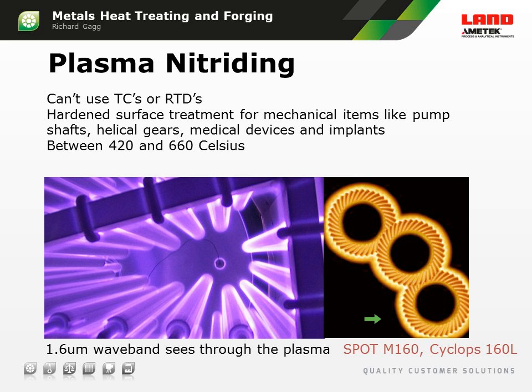And so it can be used for years and years and years and not crack, because it is slightly flexible, and only the areas which contact in the gears have this hard surface. Now, if you put a contact device into one of these plasma nitriding areas, the contact device will be contaminated by the plasma coating process. So again, the advantage here is to use a non-contact device, and in this particular case, 1.6 micrometers sees through the plasma, does not see the plasma at all. And so in this case, a Spot M160 or a Cyclops 160L would be used.